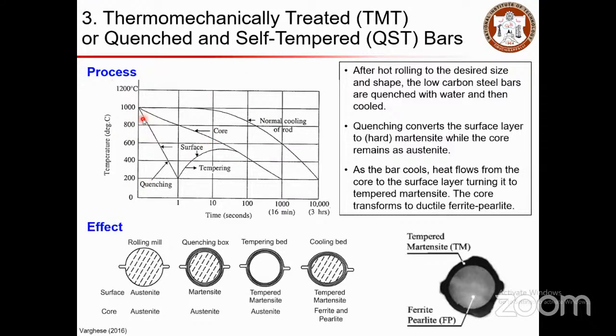The temperature will initially be increased significantly high and then it will be quenched. Then it will be kept in atmospheric conditions, so it will be tempered. By doing this process, you can immediately see the effect of this whole temperature process. After rolling, both the surface and core material will be austenite. And in the quenching box, what happens is your surface is immediately quenched. So that becomes martensite and your core will still be in the austenite stage.